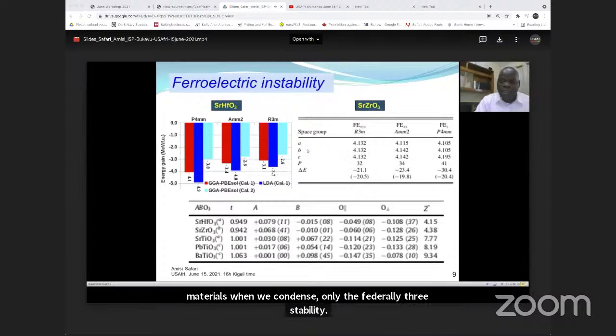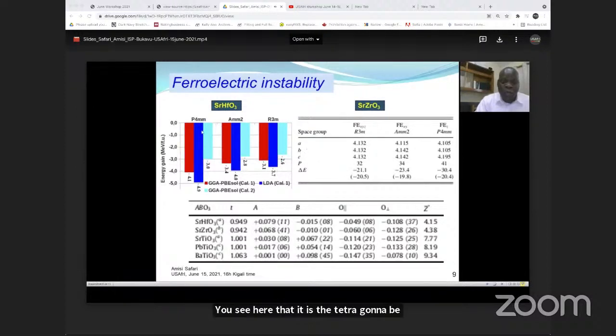You see here that it is the tetragonal P4mm which is the most energetically stable compared to the others in both compounds. And in both cases, we see a sizable contribution of the strain reduction in the stabilization of this stable ferroelectric phase, with a large relative energy gain.